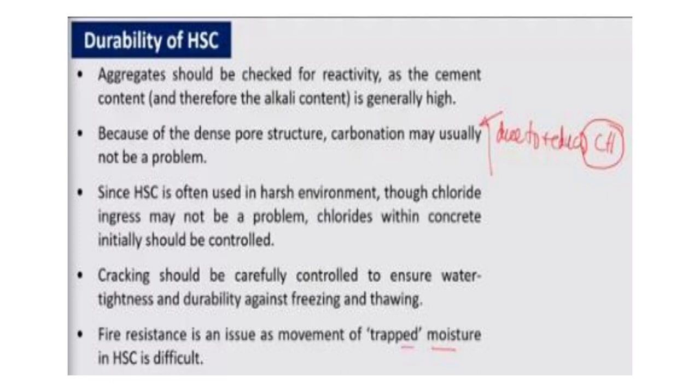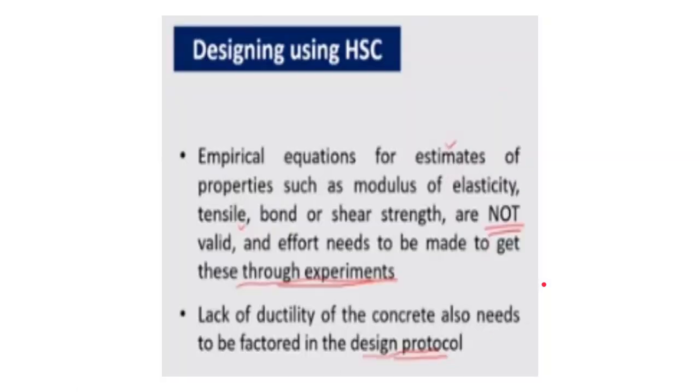And fire resistance is an issue, as movement of trapped moisture in HSC is difficult. Because heat is not able to go away, fire resistance is an issue, as the trapped moisture is not able to move easily because of the dense microstructure.